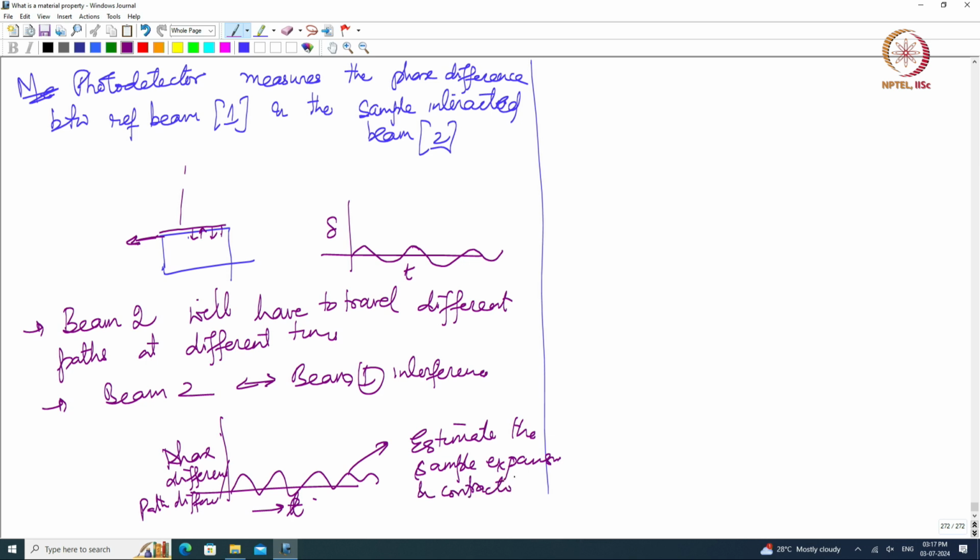It is a very neat technique, especially if I am doing it at higher frequencies, right. If I am doing these measurements at greater than 1 kilohertz, I will have picometer sensitivity. Okay. So it is a beautiful technique, you can measure picometric displacements. If I measure displacement directly, I can do the small signal measurement to actually get the change in displacements.